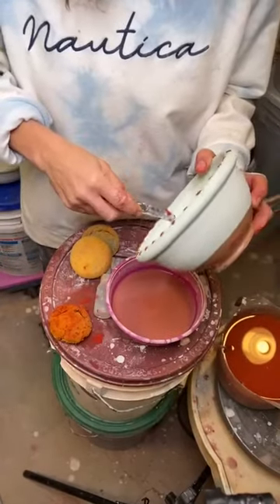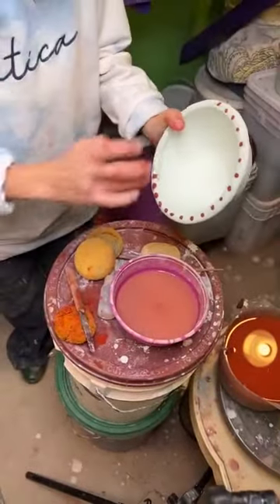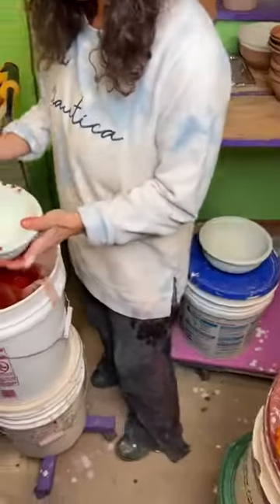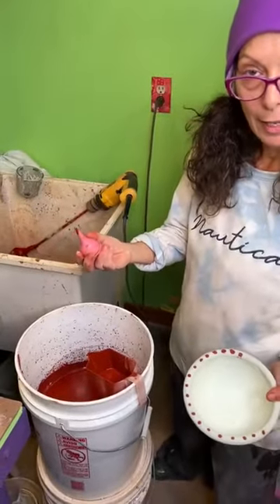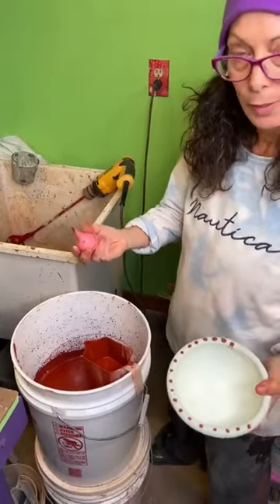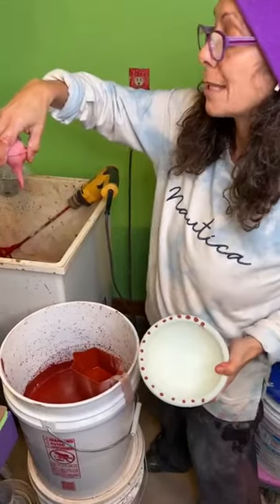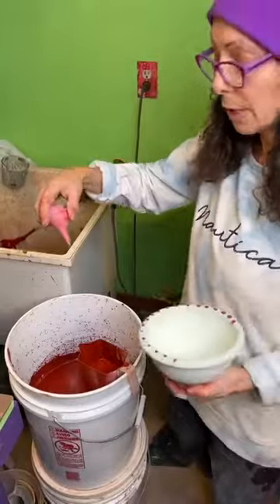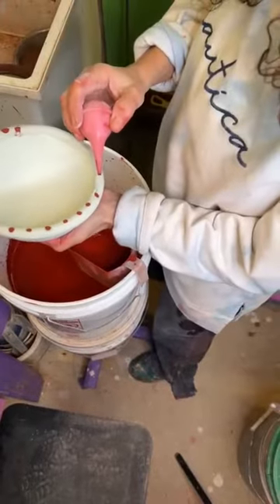Not great but not terrible, better you can say. Here's a little tip: if you want the glaze to be thick — pay attention everyone — you can turn it upside down without giving it any pressure, and if it drips slowly like that, I can handle it, I can be in control. If it just runs right out, it has to be thicker than that to work with precision with one of these bulb syringes.